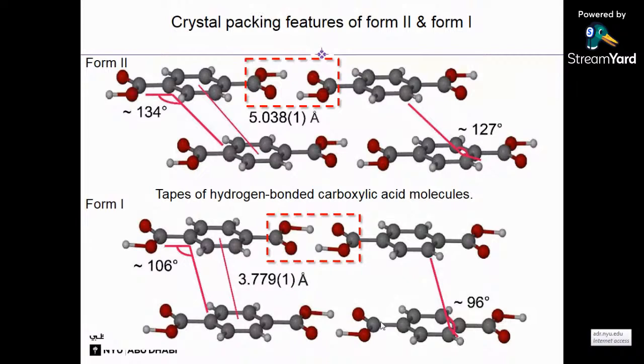The only difference between these two forms, this is single crystal data for both form 1 and form 2, is the pi stacking. As you can see here, the hydrogen bondings are intact. The distance changed from 5.038 angstroms to 3.779 angstroms during the phase transition. This is the only change happening during the phase transition.